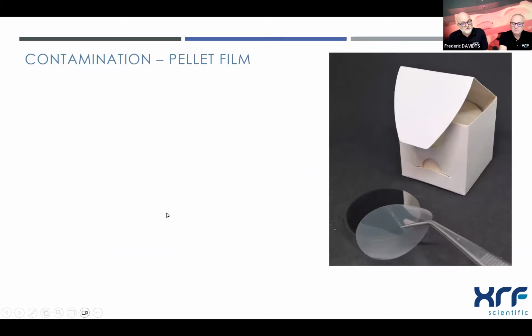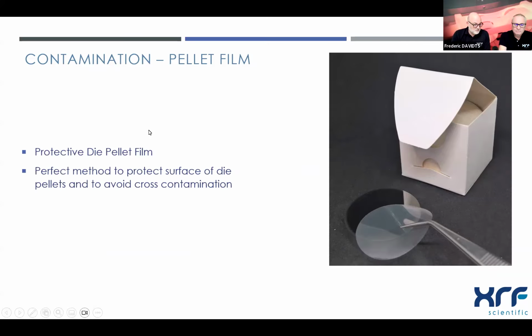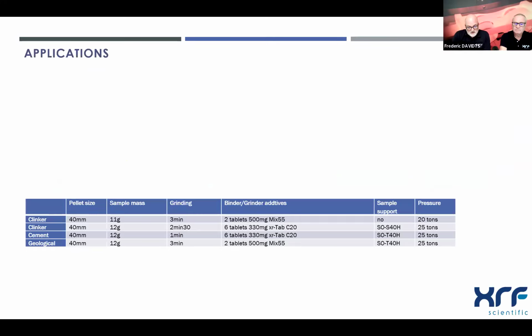Like you explained, if we have risk of contamination, it could be interesting to add a pellet film, polypropylene 12 micron, on the polished disc, or on the piston directly. So it avoids cross-contamination, or if you have powders which can corrode the disc, or if you can have potential contamination by the disc itself. So if it's made in stainless steel, you can have some contamination of the metals.